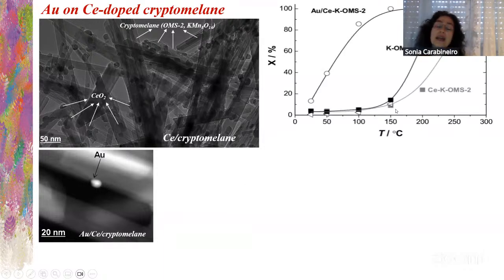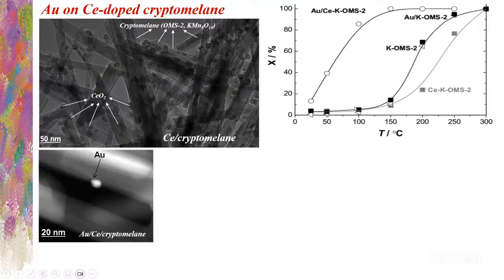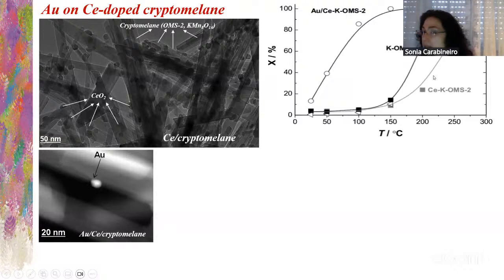So if we compare here the activity, this is gold with cryptomelane. So cryptomelane alone and cryptomelane with gold is the same. So we add gold to cryptomelane, nothing happens. If we add cerium to cryptomelane, the activity decreases. But if we add gold to the cryptomelane with cerium, you see here this large increase.